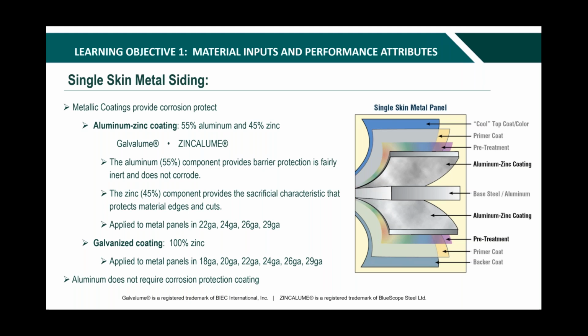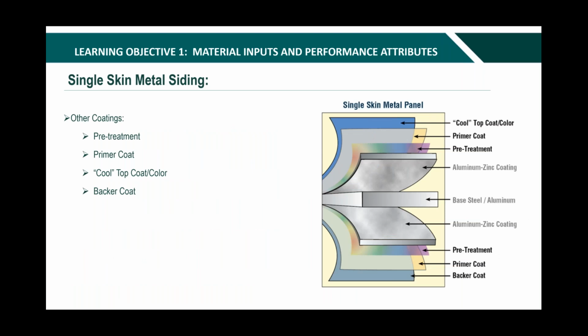And the galvanized coating is 100% zinc, and can be applied to materials as thick as 18 gauge all the way up to 29 gauge. Aluminum does not require corrosion protection coating. So unlike steel, aluminum is not coated with a different metal to protect it from the elements. The other coatings that go on during this process are the pre-treatment, the primer coat, the cool top color, and then the backer coat, of course, which is what would be shown on the underside of the metal or on the back, if you will.